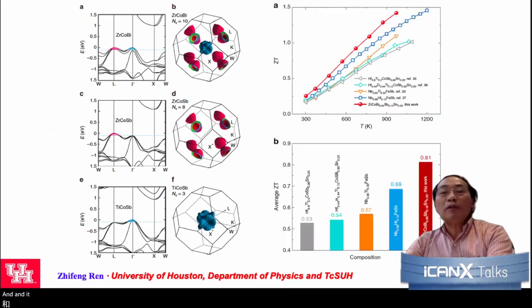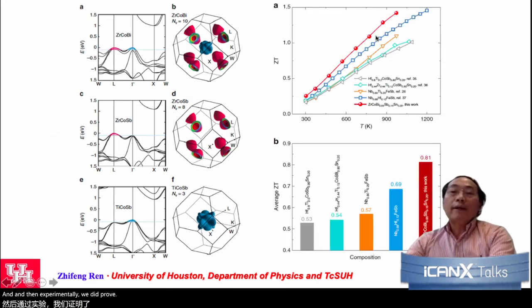And then experimentally, we indeed proved that this zirconium cobalt bismuth with some dopant has a very high ZT at about 600 degrees C. We got ZT close to 1.5. On average, the ZT is better than the previous half-Heuslers. This is probably going to be a very promising material for future power generation at a hot side temperature close to 700 degrees C. Okay.